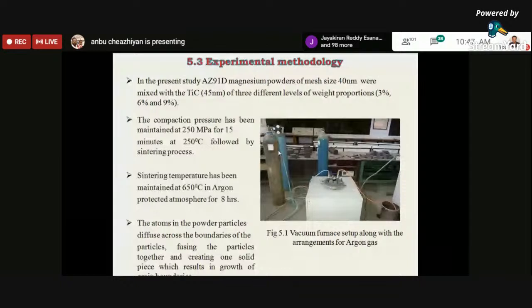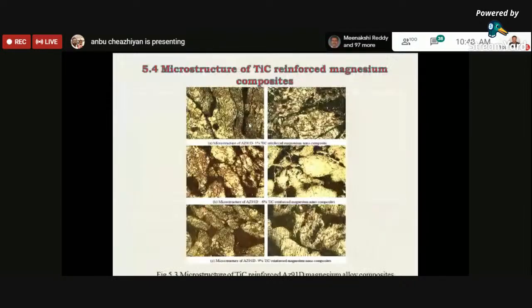The compaction pressure was maintained at 250 megapascal for 15 minutes at 250 degrees centigrade, followed by the sintering process. The sintering temperature was maintained at 650 degrees, and the sintering atmosphere was maintained for 8 hours continuously, so that the material gets diffused. During this, the atoms in the powder particles diffuse across the boundaries of the particles, and hence fusion of particles takes place, creating one solid body, which results in improvement in grain boundaries.